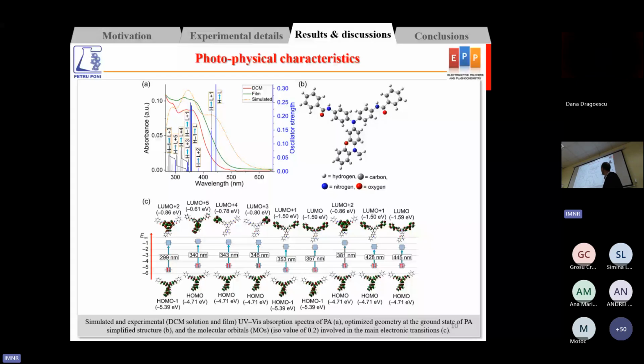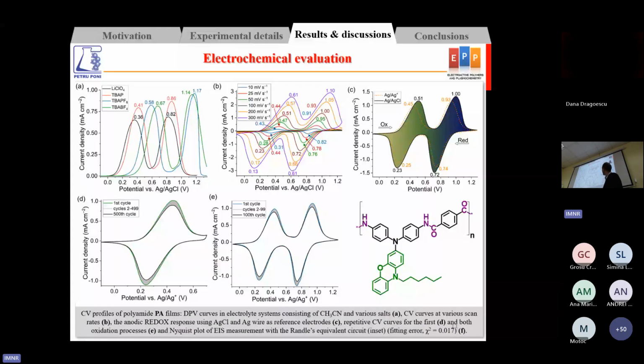Then we evaluated the electrochemical aspect of the polymers. First, we made differential pulse voltammetry in various important electrolytes, including various salts and solvents, and lithium perchlorate in acetonitrile proved to be the most suitable supporting electrolyte. With this condition, we moved forward and evaluated the cyclic voltammetry of the polymers at various scan rates, and we can see that the polymers didn't highlight any secondary reaction except the two main oxidation processes belonging to the diphenylamine and phenoxazine unit.